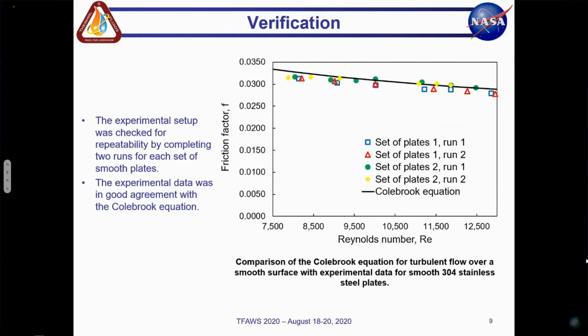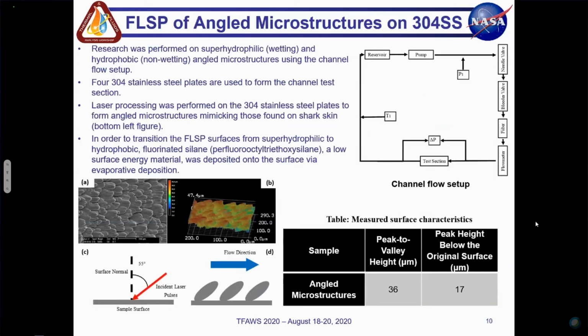As I mentioned, we used multiple sets of plates to check the repeatability of the system itself. 2 runs were done for each set of smooth plates. We started at the lowest flow rate that we could get, around 8,000, and went to roughly 13,000 Reynolds number using the same pressure differential. So we didn't have any issues switching out any measurement devices. And then we did these over multiple assemblies, and for both sets of smooth plates, we were able to get reproducible data that was in agreement with the Colebrook equation that you saw Hartnett use in the previous slide.